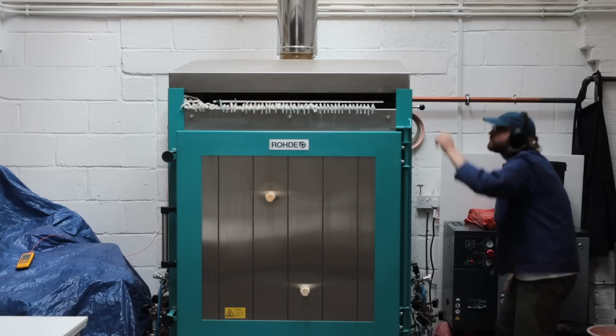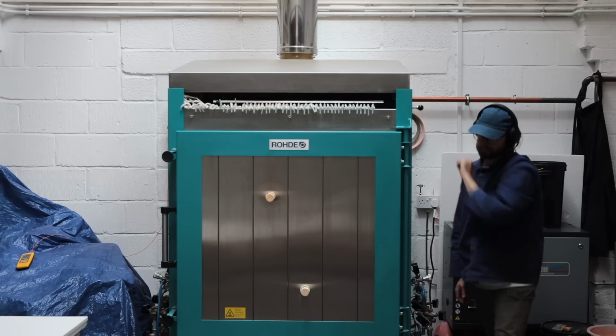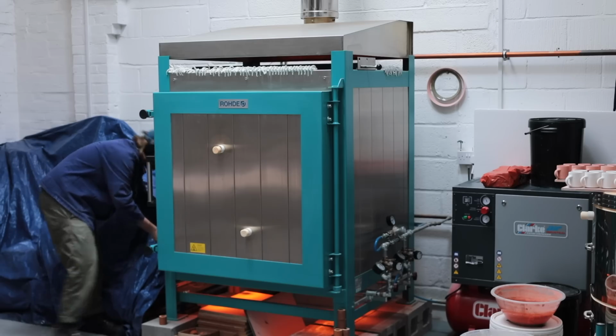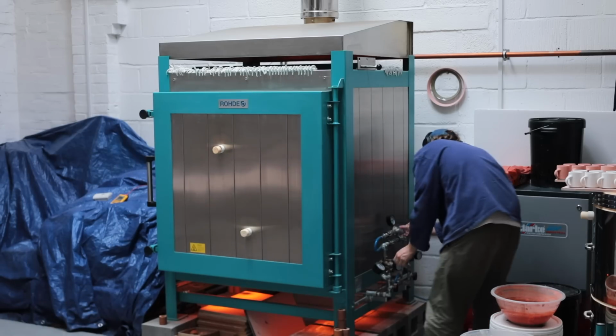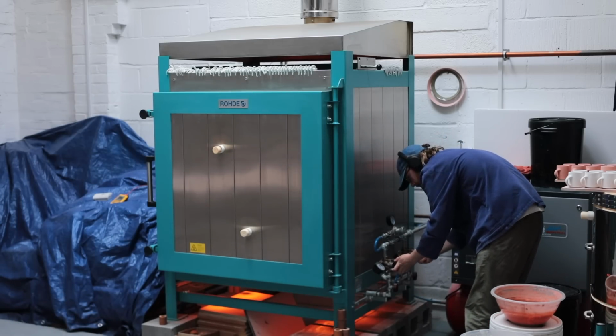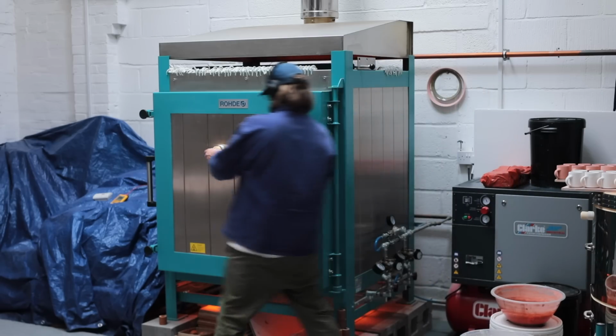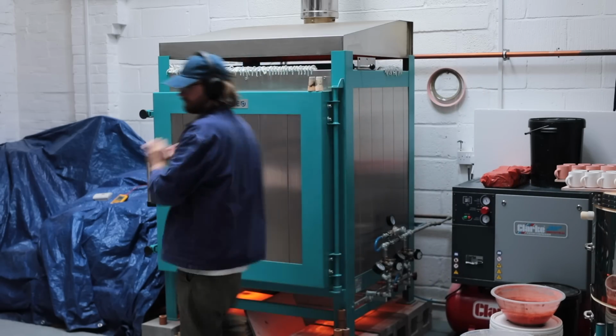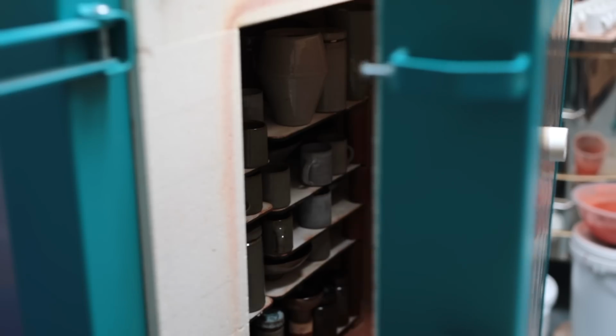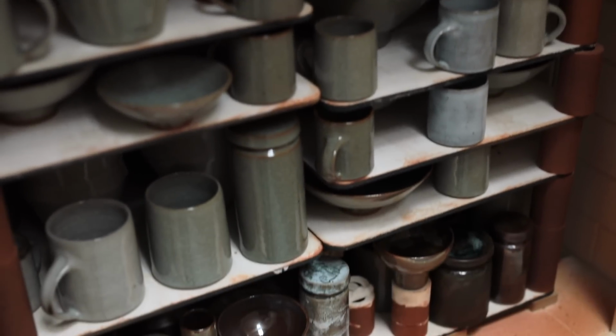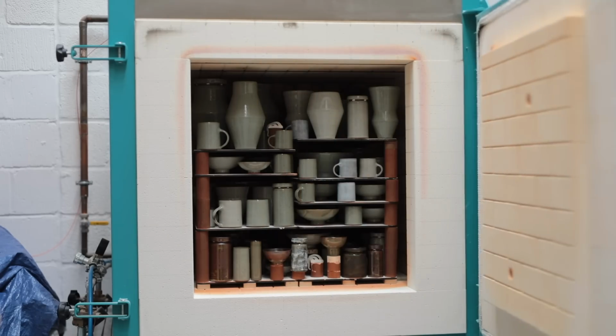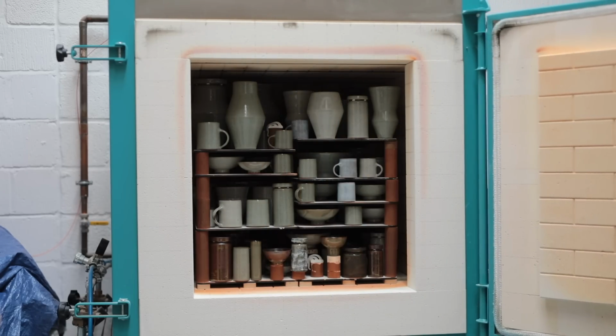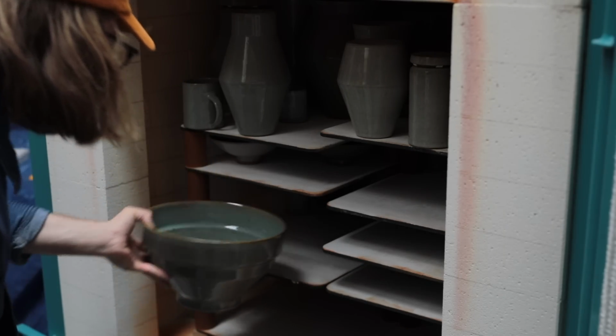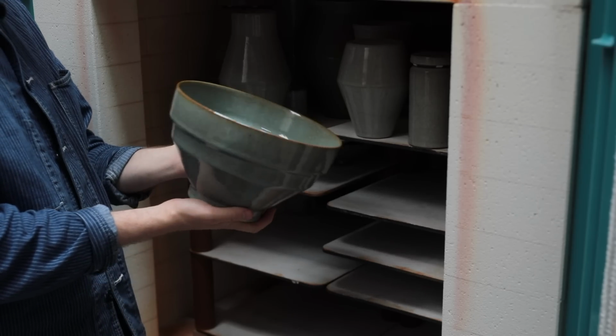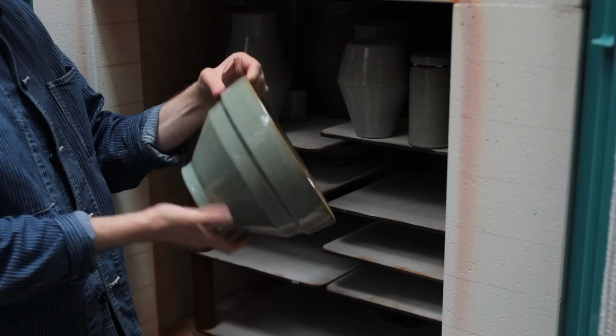At exactly 860 degrees Celsius, reduction is initiated, and then once cone 10 is flat, at about 1290 degrees Celsius, the kiln can be switched off and the firing concluded. From this point, the kiln will take about 2 days to cool down, before the door can finally be opened. And here's the first of those 2 bowls, and seriously, to my utter shock, even with all that faffing around with the glaze, they fired perfectly, which I honestly didn't expect to happen.